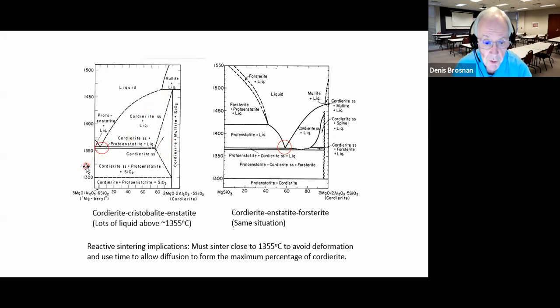If you get off the composition a little bit, you're going to see some pretty low melting temperatures down around 1350. The peritectic temperature is here, above 1450 or thereabouts. So you really got to worry about these temperatures down here. Remember that I've tried to teach you that in firing a ceramic, the first liquid that's going to be formed is the lowest eutectic in the system. Even though the overall composition might not suggest that, you can form that liquid. Now, as you continue firing, that liquid composition will gradually go toward the overall composition, toward cordierite, and disappear. This is what reactive sintering is all about. So keep in mind 1350 and up here above 1450 where we get up to the peritectic temperature.